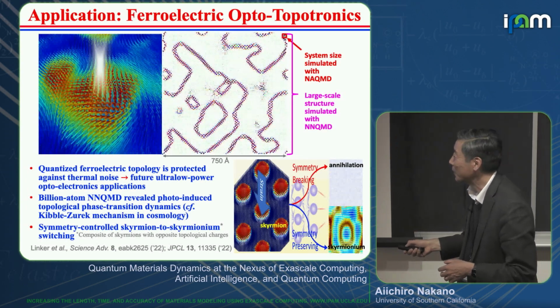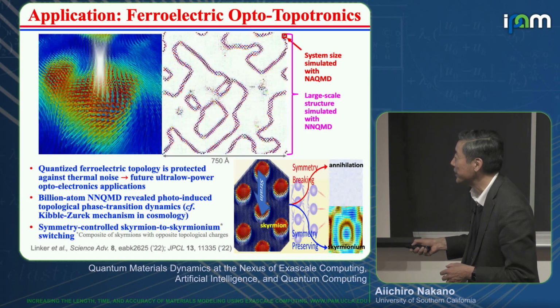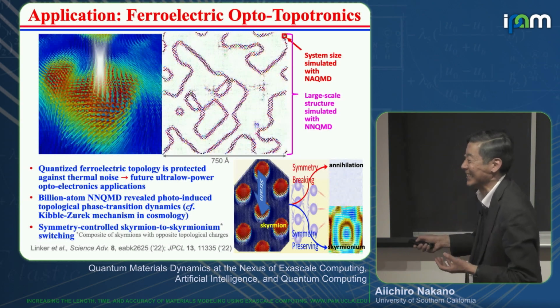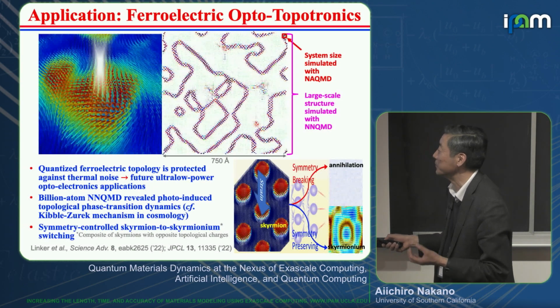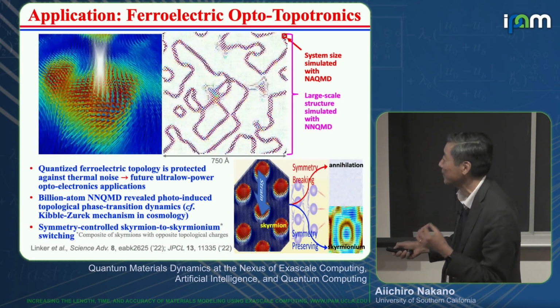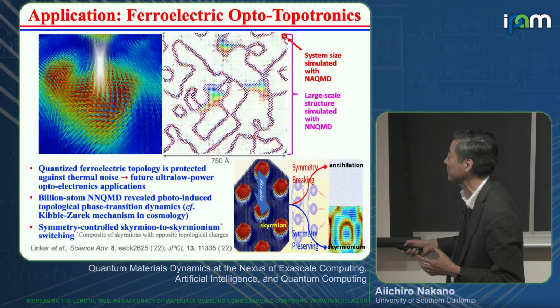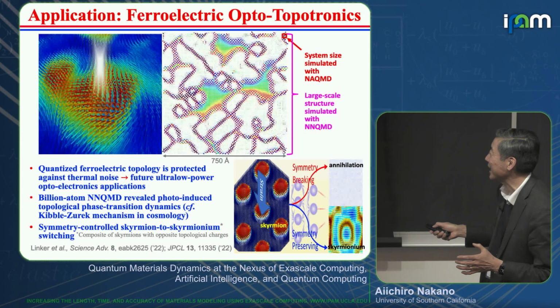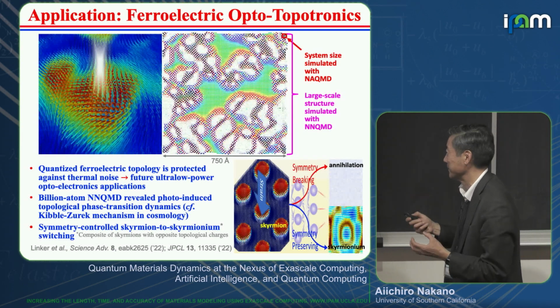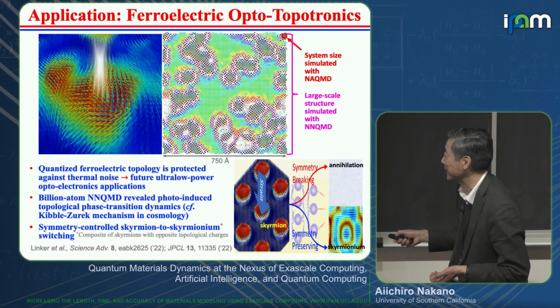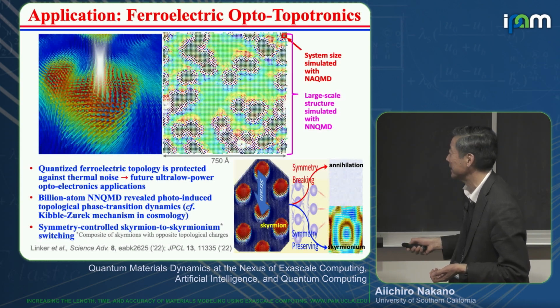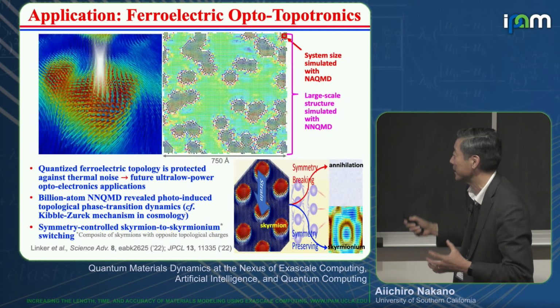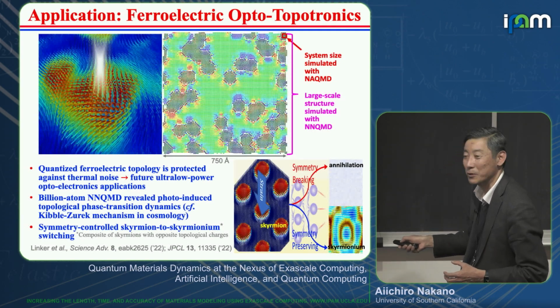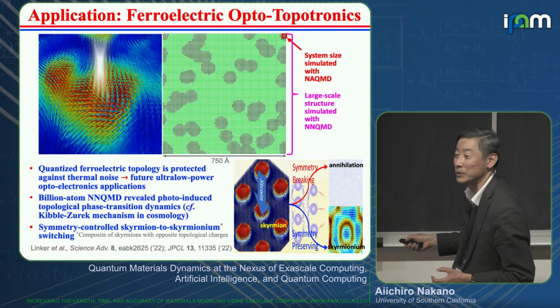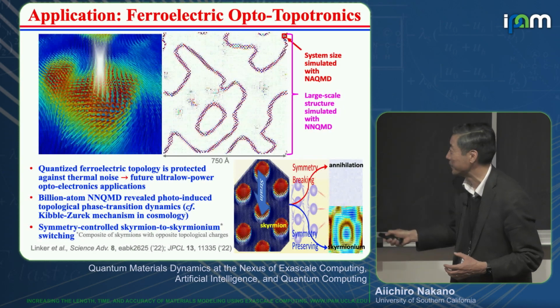We also observed symmetry-controlled skyrmion to skyrmionium switching. Sorry, I cannot pronounce it. Here, skyrmionium is a topological composite of skyrmions with opposite topological charges. But we found that under symmetry-breaking strain, we can annihilate this skyrmion topological defect. On the other hand, if you do symmetry-preserving compression, then you can convert one skyrmion to a skyrmionium. So again, that topological change can be controlled by symmetry.